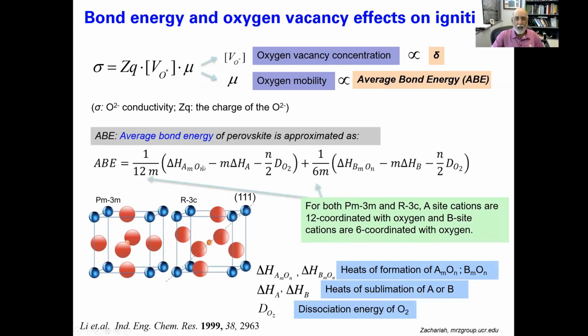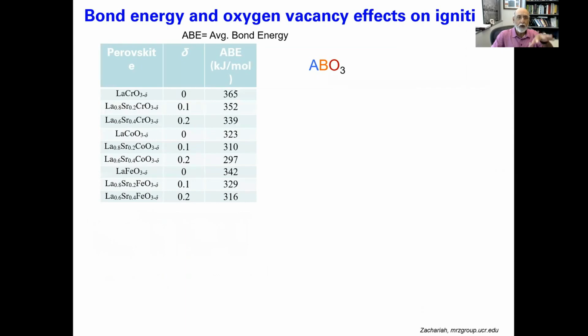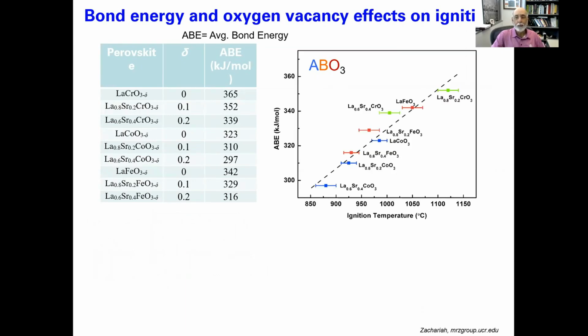Now we can estimate the average bond energy. There are people who have figured out rough calculations using bond enthalpies of reactions for binary systems to estimate average bond energies in complex systems. We're going to use that. So I'm going to take all our data and I'm going to put it versus the ignition temperature. So this is our experiment on the x-axis. This is our measured ignition temperature. This is the calculated bond energy. And amazingly enough, you can see it follows a trend quite nicely. That is that ignition and bond energy are related.